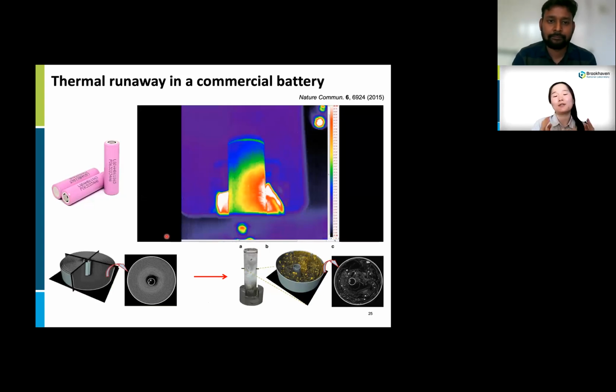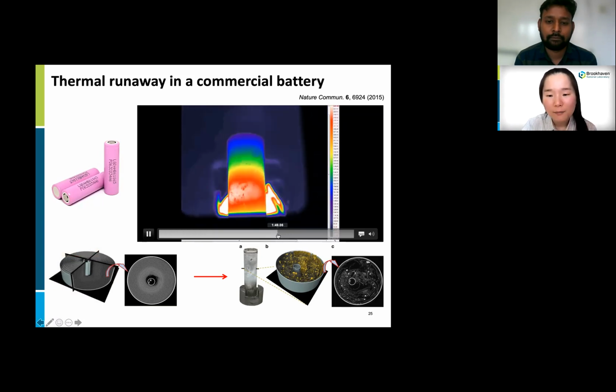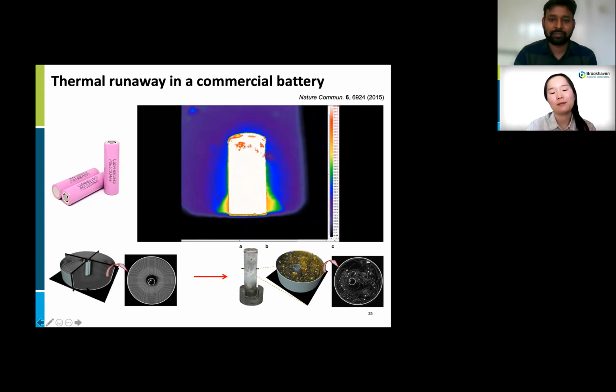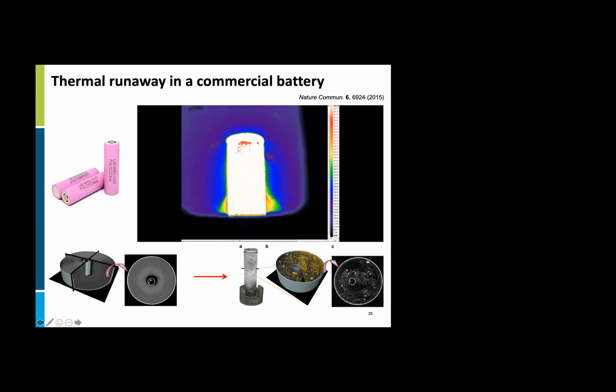Thermal stability is an important factor for battery safety. So this is a commercial battery, and a researcher in the UK recorded the temperature inside the battery while increasing the temperature outside. At first, the battery itself can manage the temperature pretty well, but at some point, we can see hotspots in white. And eventually, at some point, this battery experiences an explosion. And from X-ray tomograms before and after breakdown, we can clearly see that the internal structure was hugely damaged.